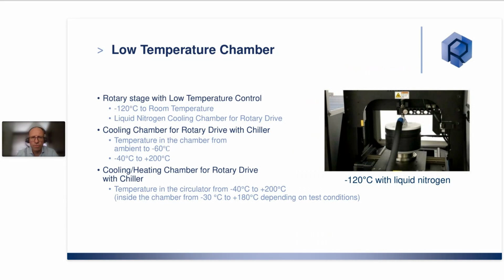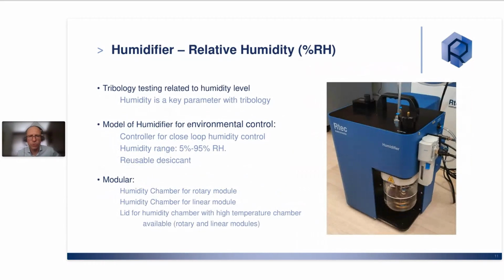the low temperature. It is true that depending on the liquid which is used, in the case of liquid nitrogen, you can go to very low temperature, minus 120 degrees Celsius, but it's also possible to use other kinds of liquid in order to go to minus 40 or minus 60 degrees Celsius. The other evolution that we had was the possibility to offer a new humidifying system or humidifier in order to have in a closed chamber the possibility to control the level of humidity.